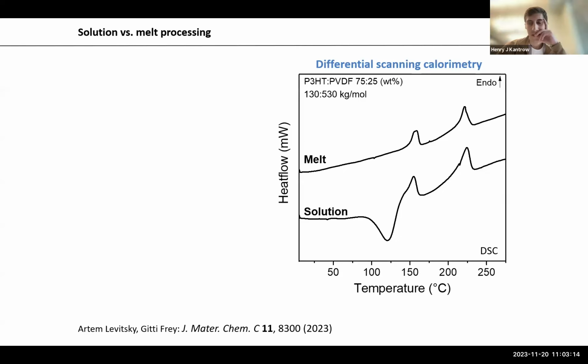Yeah, I was going to add to that, I guess, what we see is, I think, more an aggregation effect, right? When you add the PVDF, we're affecting the nature of the P3HT aggregates, which I think are potentially more stable. Even if you go above the cold crystallization temperature, you have not yet disrupted that aggregate that you formed from the solid state.